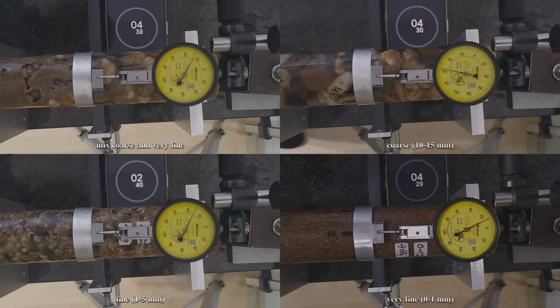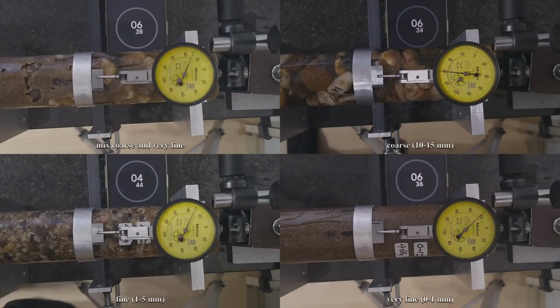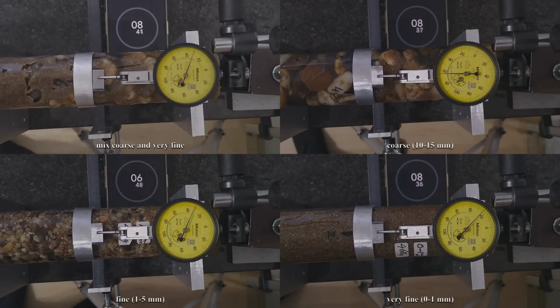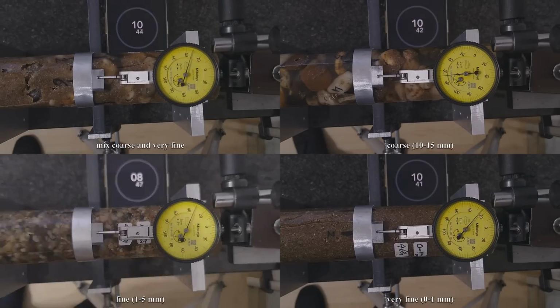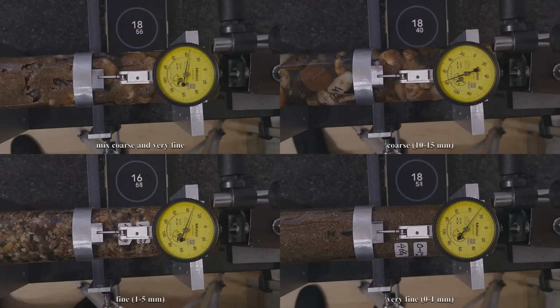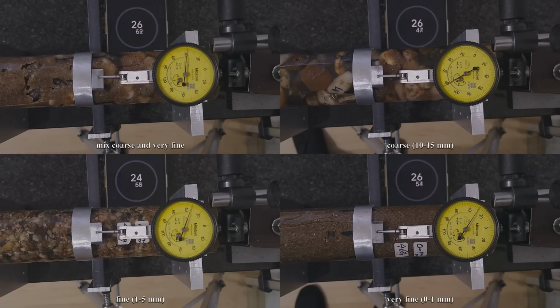The deflection under longer-term loads has also been tested. After 10 seconds, very fine is the best, with 24 microns of deflection. Fine and the mixture are equal to 32 microns, and the rod with the coarse pebbles is clearly the worst in deflection at 68 microns.